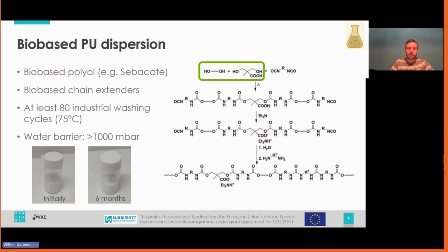One of those ways is bio-based polyurethanes. So this is almost like Lutz mentioned, a drop-in material. So currently, fossil-based polyurethanes and polyurethane dispersions are used quite commonly in textiles. For example, for waterproof clothing like rain jackets, polyurethane coatings are used. What we do here, instead of using a fossil-based component, we replace this component, the polyol, with a bio-based alternative. In this case, for example, a sebacate-based polyol, and we then use this polyol to make polyurethanes.